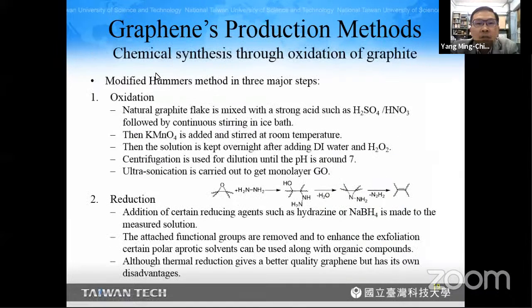The modified Hummers method is done in three major steps. The first is oxidation, where natural graphite flakes are mixed with strong acids such as sulfuric acid and nitric acid, followed by continuous stirring in an ice bath. Then potassium permanganate is added and stirred at room temperature. Then the solution is kept overnight after adding deionized water and hydrogen peroxide. Following that, centrifugation is used for dilution until the pH is around 7. And lastly, ultrasonication is carried out to get monolayer graphene oxide.